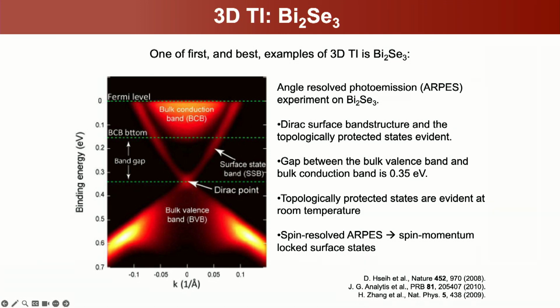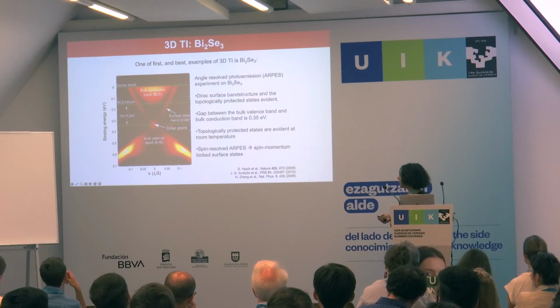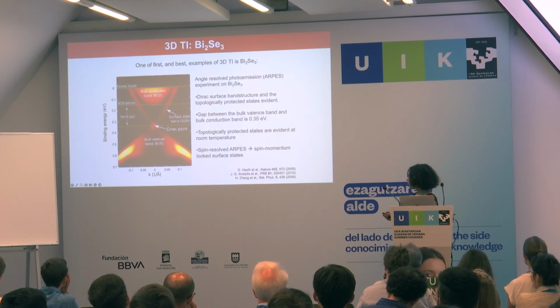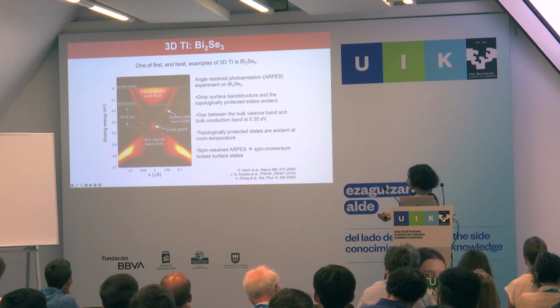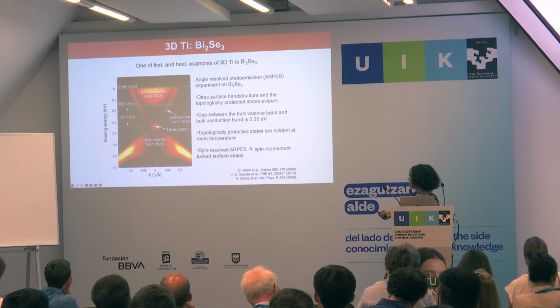And that's also really important because if you want to think about or use or even measure these, it's nice to not always have to go down to very low temperatures. And the spin momentum locking states have been determined by spin resolved ARPES as well. So many of these properties have been experimentally determined. Now, one of the issues in studying these materials, of course, is that what we want to do most of the time is tune in and out of the topological regime, which would be, ideally somewhere right around the band crossing would be the Fermi energy, and then we just tune up and down and never deal with the bulk